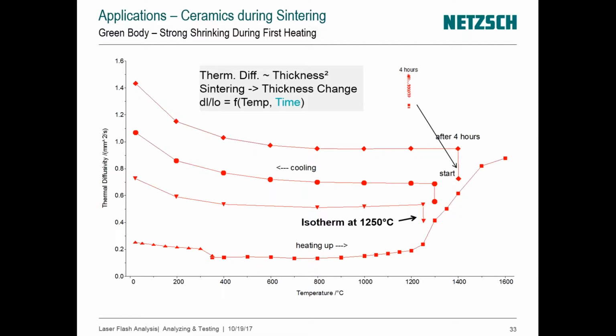Now, if we do have this isotherm and we keep it long enough, in that case 4 hours at a much higher temperature, in that case 1400 degrees C, and then we keep measuring the diffusivity cooling down, we see that we obtain a much higher diffusivity. The purpose of this is to show you that the sintering is important. The temperature of sintering is very important.